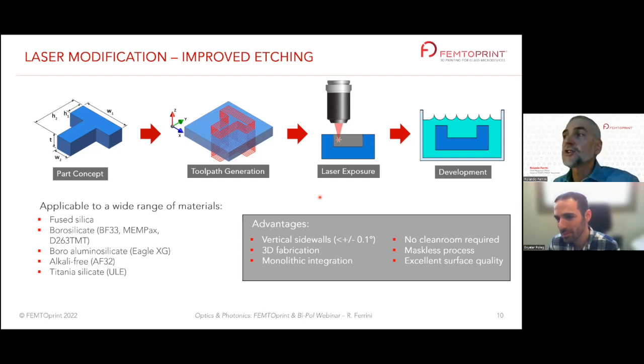I will come to this later, but this is through a post-process. Out of this process, you still have a residual roughness, which is in the order of hundreds of nanometers, which is not enough for optical applications. What we have developed is a special surface treatment that allows us to reduce the roughness down to 10 nanometers or below. So today we can produce components with optical grade. I will give you some examples later on.